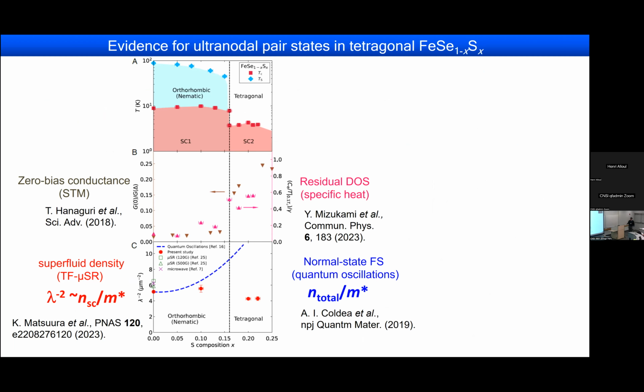Okay, so here is the kind of experimental summary. First, the phase diagram shows a kind of jump in TC, and then zero bias conductance from STM, which is plotted by these brown symbols, and also residual density of states plotted by pink from spectroscopy. All of these show the jump if you go into the SC2 phase, okay?